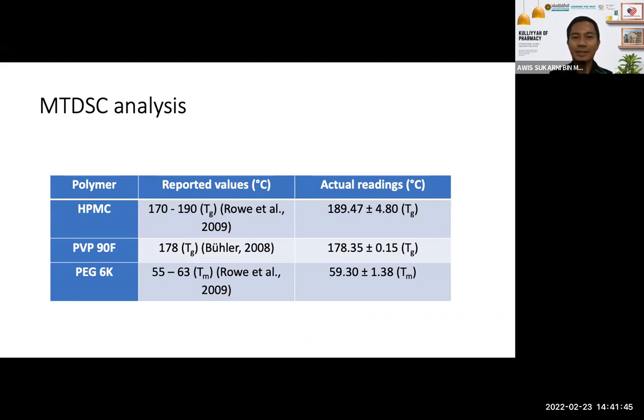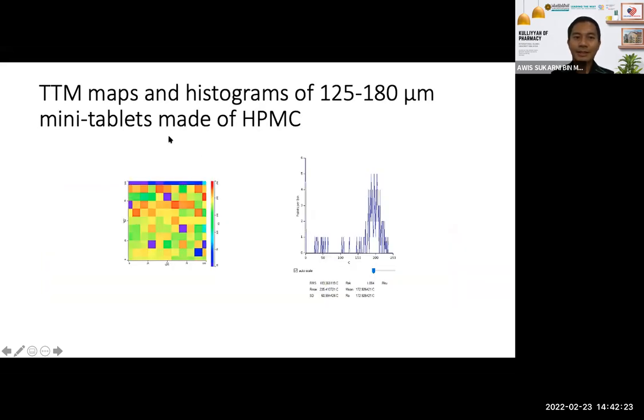Before I start the study, I ran the sample using the MTDSC, which is the modulated temperature differential scanning calorimetry, just to test what is the actual reading of the sample that I use. This one is the value that I got from the reported value from this article, and this one is the one that I got from the MTDSC analysis. As you can see here, all the readings agree with the ones that have been reported by other researchers here.